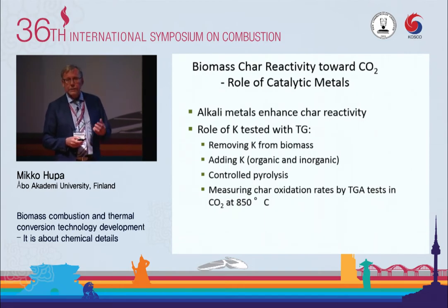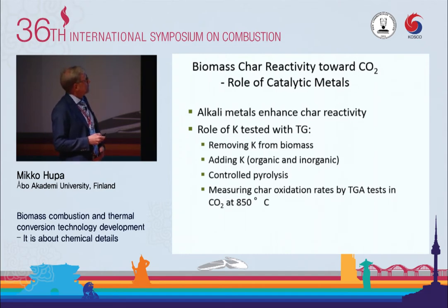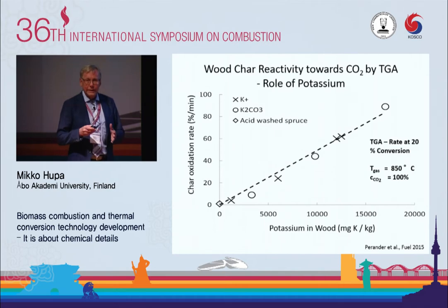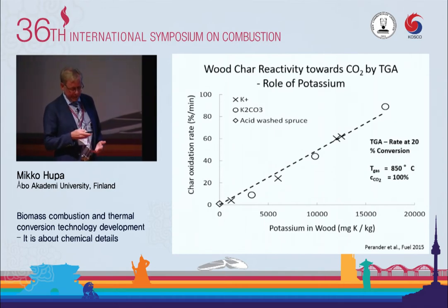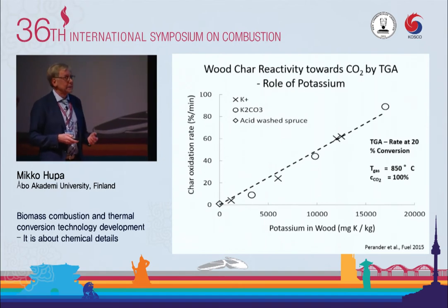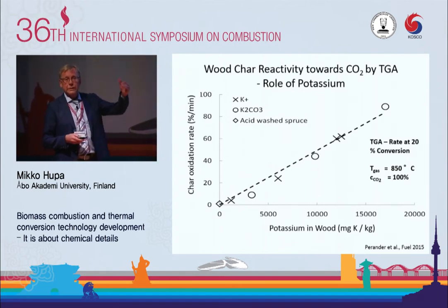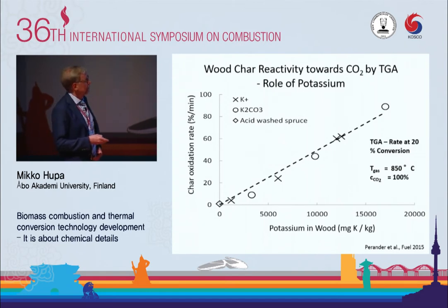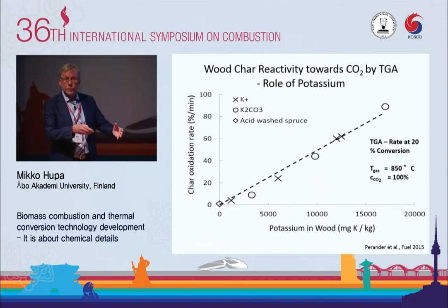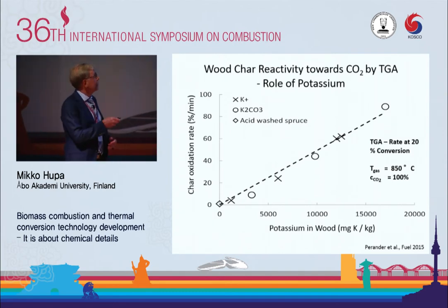That higher reactivity has to do with the ash ingredients in biomass. And now we come back to particularly the alkali metals and potassium. And quite recently, we wanted to learn a little more about which factors affect the char reactivity, and we took biomasses and produced chars with different content of potassium, just to see how the potassium influences. And here we have a biomass which we had completely washed before producing the char. So the potassium content was zero.